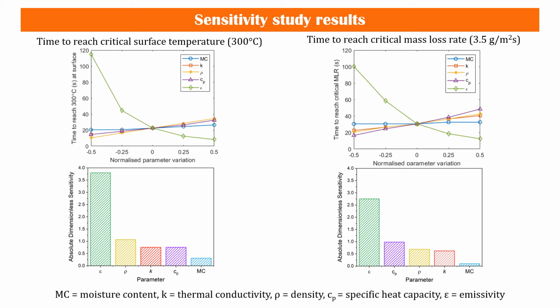Both ignition criteria show a low sensitivity to moisture content. This is unexpected and contradicts the literature. High moisture content will require a prolonged drying reaction time, as the energy required to evaporate the water will be greater.